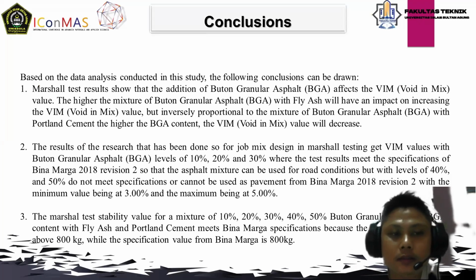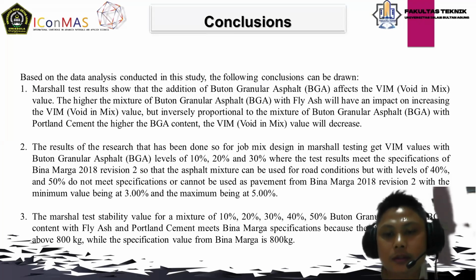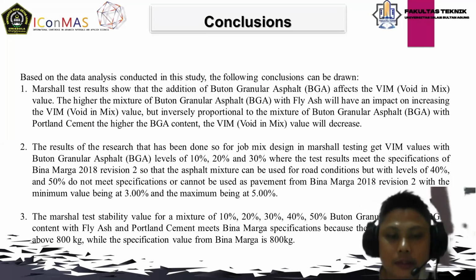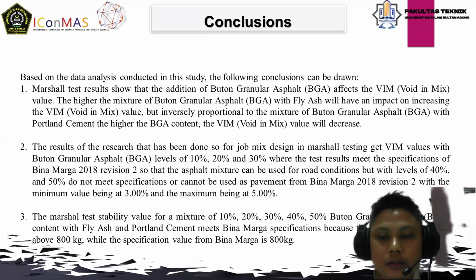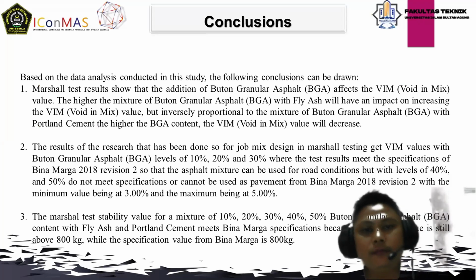The other result is the result of research that has been done for Marshall testing with BGA levels 10, 20, 30, where the result meets the specification from Bina Marga. And number 3, the Marshall stability value for a mixture of 10, 20, 30, 40 BGA content with fly ash and Portland Cement meets the specification. About 800 to 1000 kilograms for the specification for the Bina Marga reference. I think this is the conclusion.